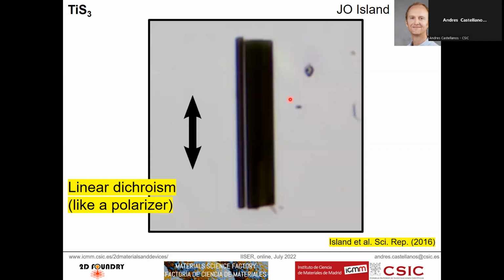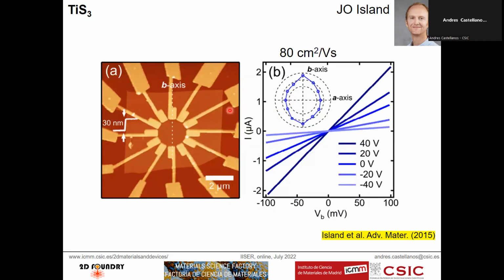So now we can actually measure this anisotropy in the electrical properties of the material. We can take one of these flakes fabricated by mechanical exfoliation, and we can pattern electrodes at different angles. So we can measure between this and this, between this and this, in order to get information about the angular difference in the electrical properties. And then we have here the mobility in a polar plot, and we get much larger mobility along the B axis than the A axis. Okay, we get mobilities up to 80 centimeters squared per volt per second, which is huge. And it makes sense because, as I said, when the light is polarized along the B axis, the flake absorbs much more light because it's the low resistance, high mobility axis here.